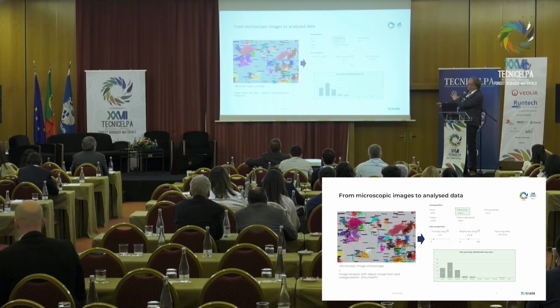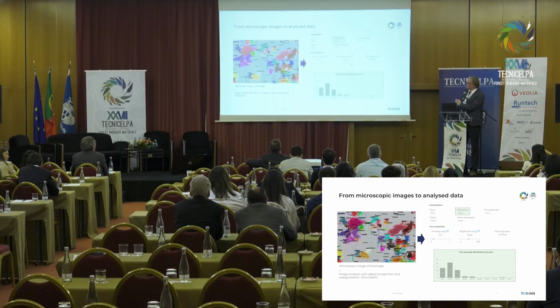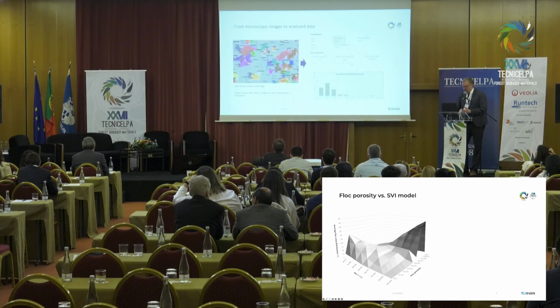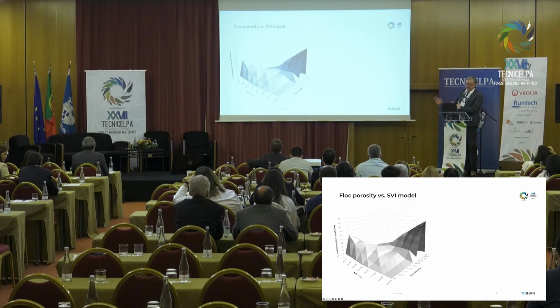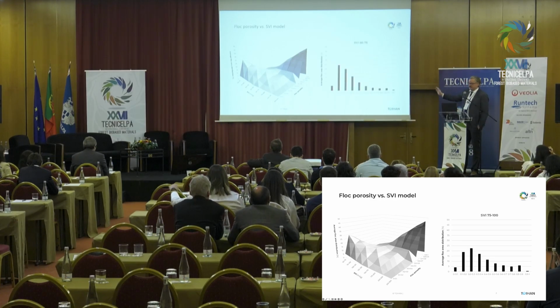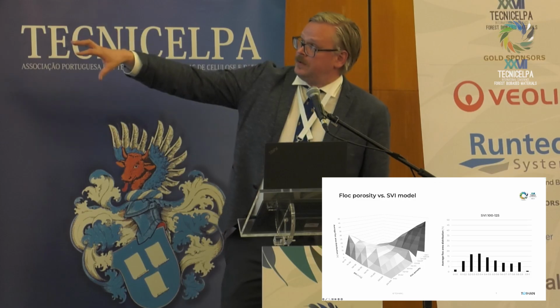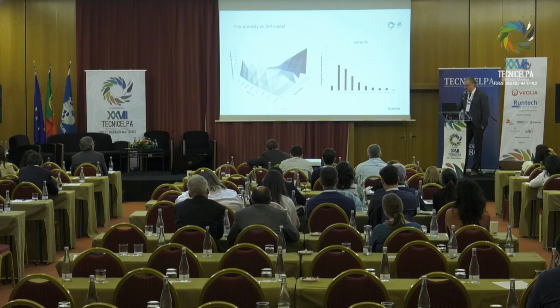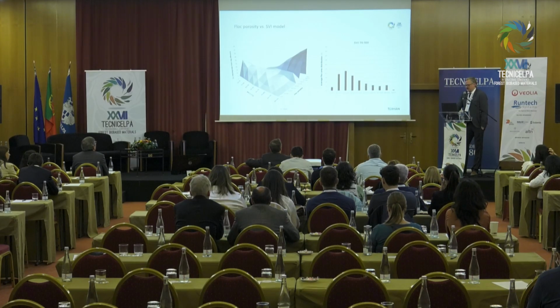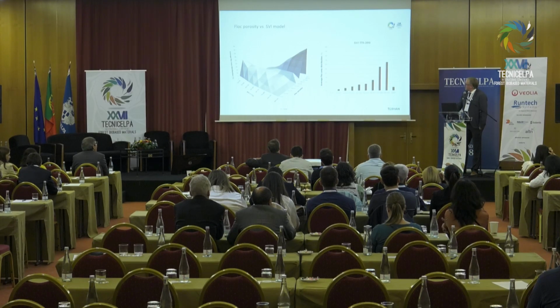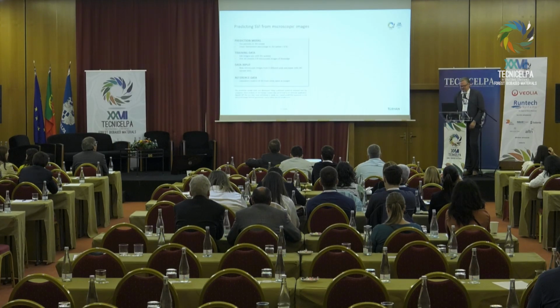If there is lots of floc with low porosity or high density, this kind of biomass would most likely settle well. So we use this kind of model that we have created, and here is the 3D model. This is an example of a well-settling sludge and porosity. You see that most of the floc are at low porosity level. And then when we have a higher SVI, meaning it does not settle that well, this distribution goes to a different kind. This is quite a poorly settling sludge, and this does not settle at all. So we use this model.